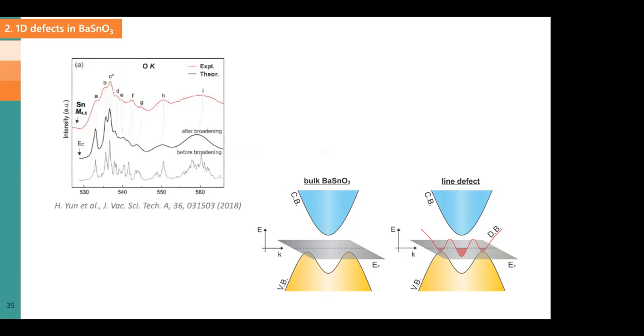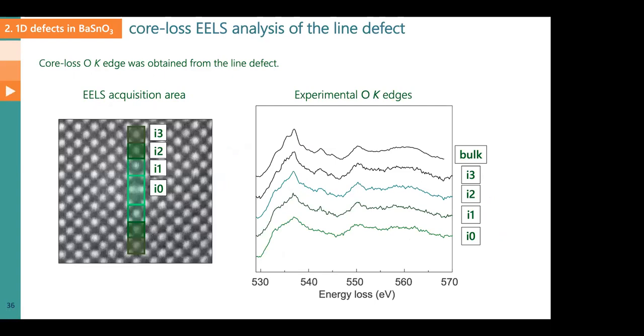And now we're going to use electron energy loss spectroscopy, which I was telling you about earlier. So that's when it's going to be really handy. What we did, we took our microscope and located the probe around the individual atoms, one at a time, and collected the EELS data.